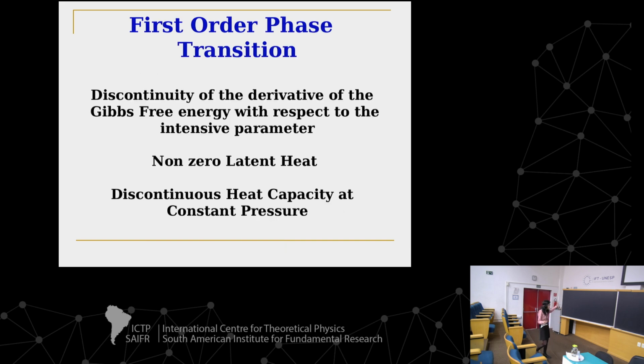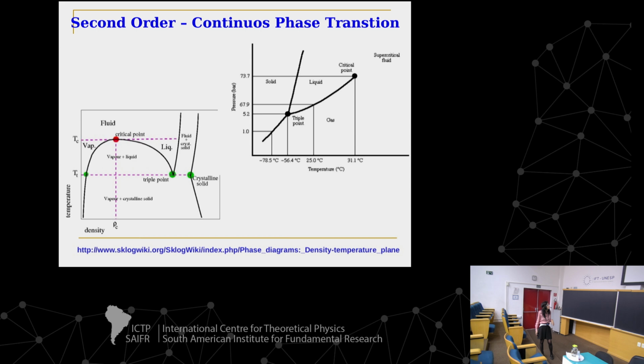So if we agree, in the first order phase transition we have a discontinuous derivative of the Gibbs free energy with respect to intensive parameters. I call them intensive parameters because I don't want to be specific that they have to be pressure or temperature, because we might use something different, okay? And we have a non-zero latent heat that is derived from the jump in entropy, and usually a discontinuity in the heat capacity at constant pressure.